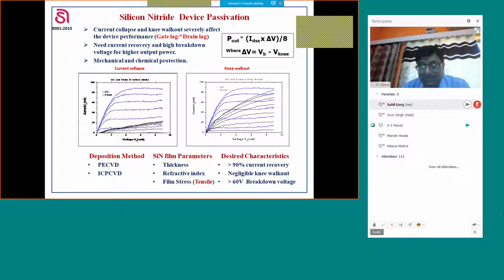So you can see that this is my DC characteristic, but once I am using a pulse IV measurement, because of the presence of these traps, and these traps are trapping my carrier electrons, current reduces drastically in pulse IV or RF mode of operation. So we will ultimately not get power. So these traps are to be passivated by this silicon nitride device passivation, and this is normally done by plasma enhanced chemical vapor deposition or inductively coupled plasma chemical vapor deposition process, and these traps are passivated.